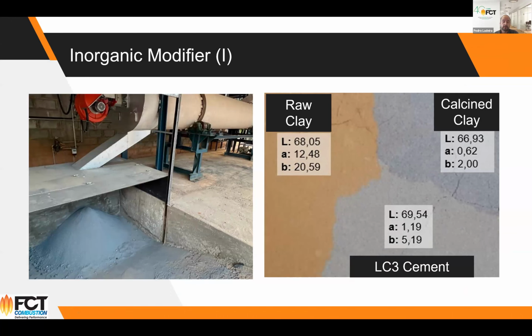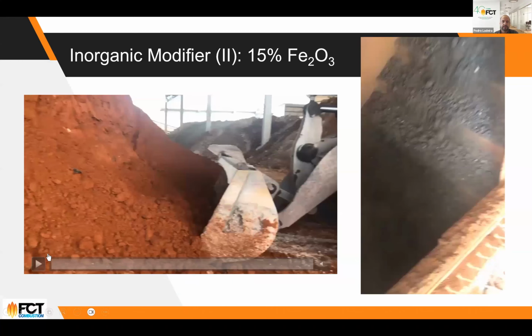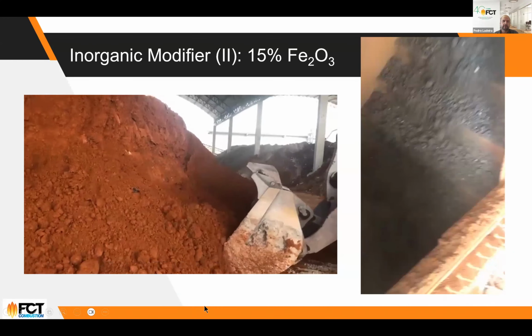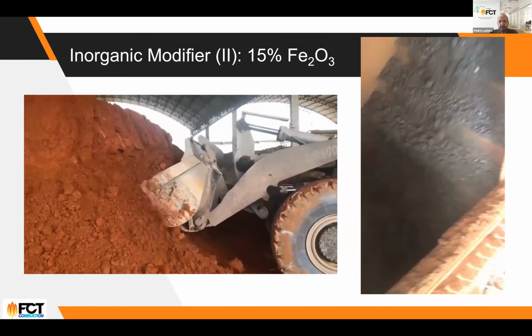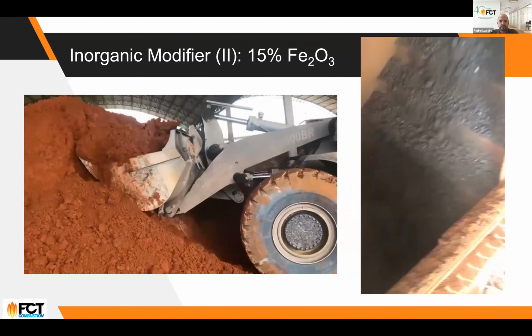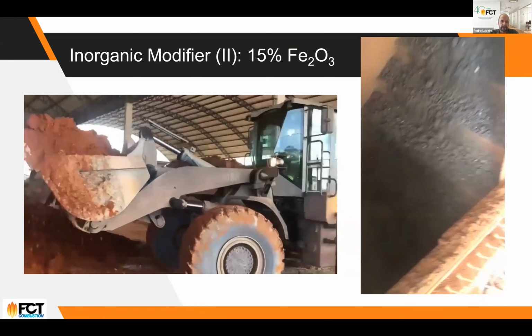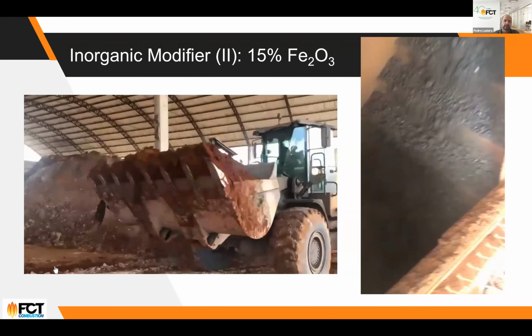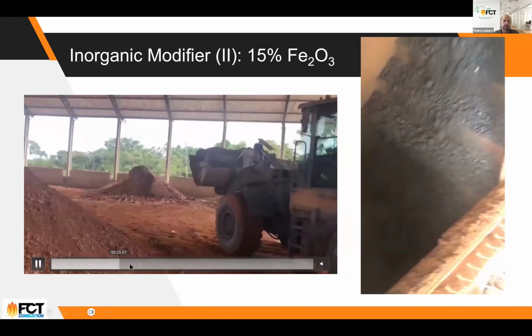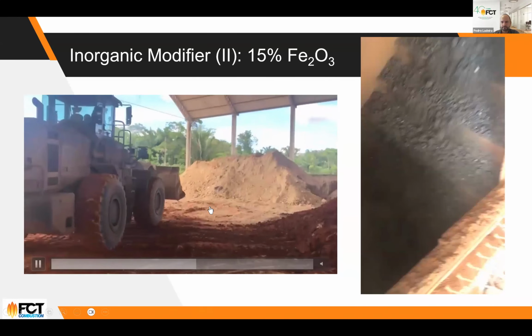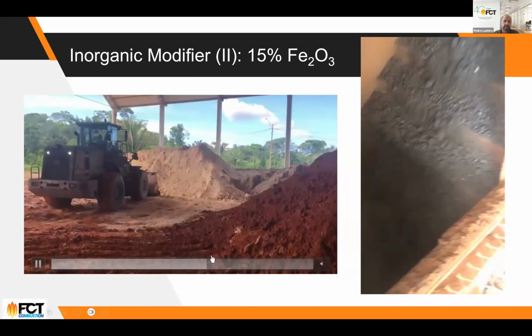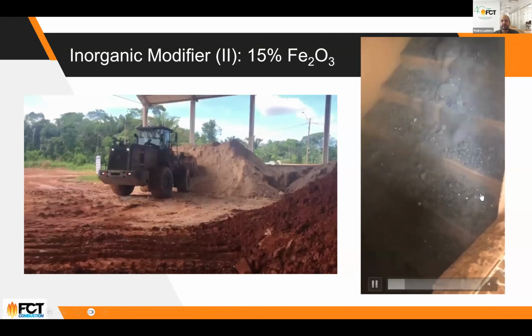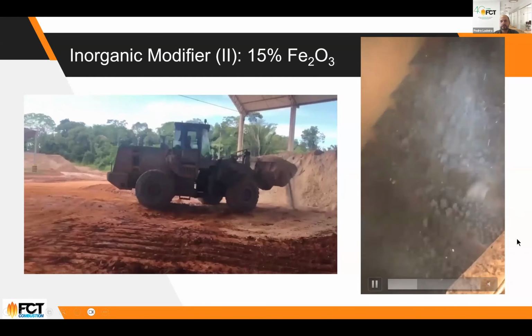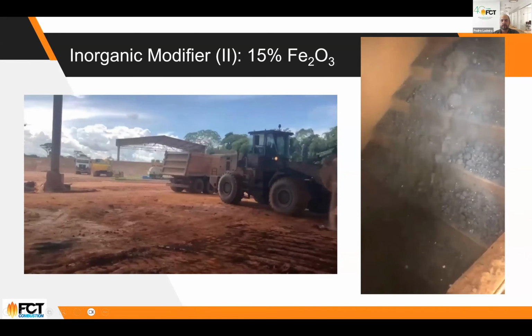So one may ask, well, would it work in real life? So a bit of what is the real life here. As you can see here, we went to an extreme situation where we have a very red raw clay, and we want it to become a gray cement supplementary material that provides gray color. So what we do is simply add this clay and blend it volumetrically to a source of calcium, which we call the inorganic modifier, that after burning gets a very gray color. So this one, we don't even have to measure the color a, but as you can see, it resembles a lot gray clinker.